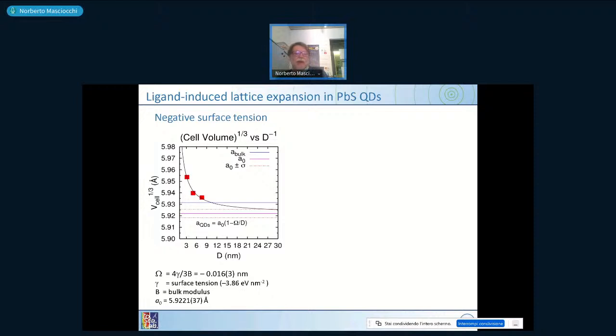Now you take the cell volume, the cubic root of the volume, and you plot, this is basically the cell of cubic edges, and you have three values, and with the three values we have we just intended to plot a curve which has this dependence. So this is the length of the quantum dots, which should be equal to a reference value modified by something which multiplies 1 over d. And this something, omega, is nothing else than the ratio between the surface tension and the bulk modulus. The bulk modulus is known, and by doing this plot, you can get the surface tension value.